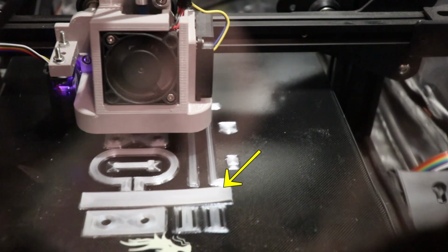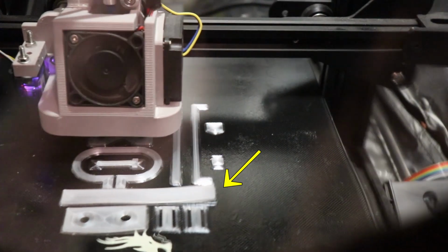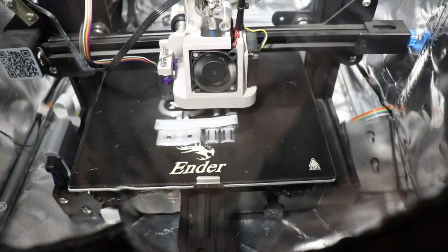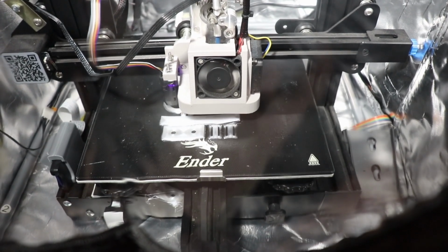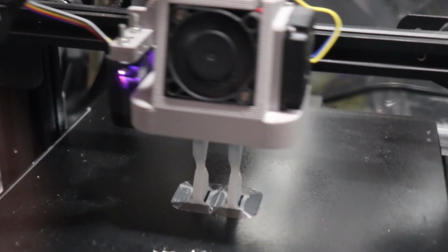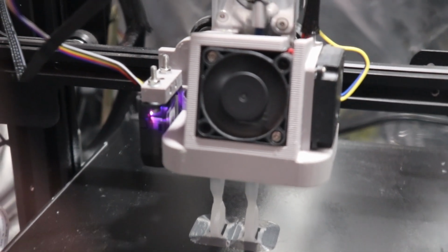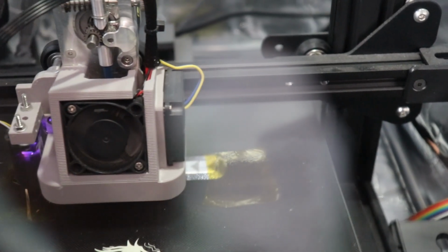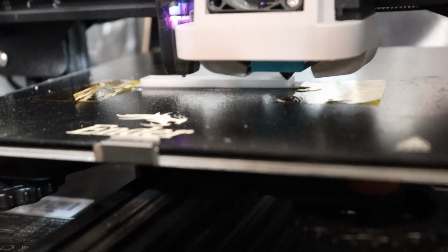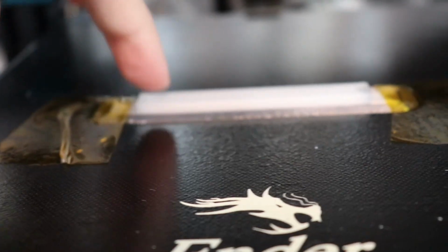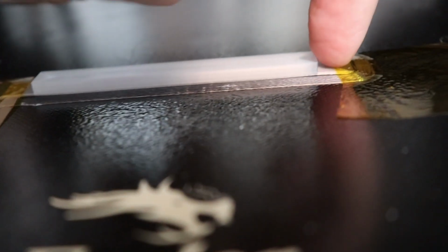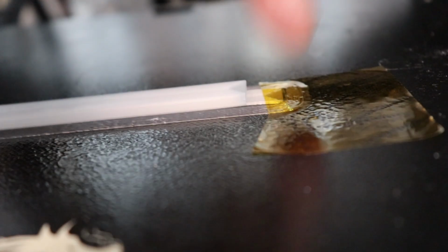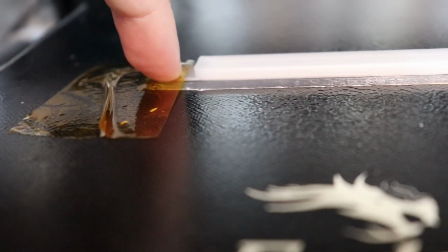First I wanted to print all test specimens at once, but the one for the bending test curled up and the nozzle hit the object and it removed it from the bed, so I decided to print all test specimens one by one. And what was my solution for that bending test specimen? Kapton tape. Not too elegant a solution, but it works. So I designed a two-layer thickness additional, let's say, brim, but this is part of the design. And then I glue it with the Kapton tape after it was printed.